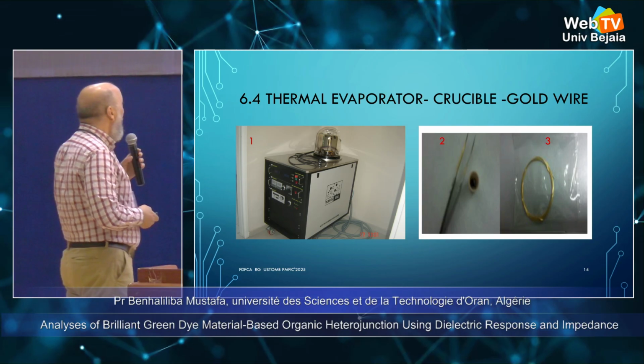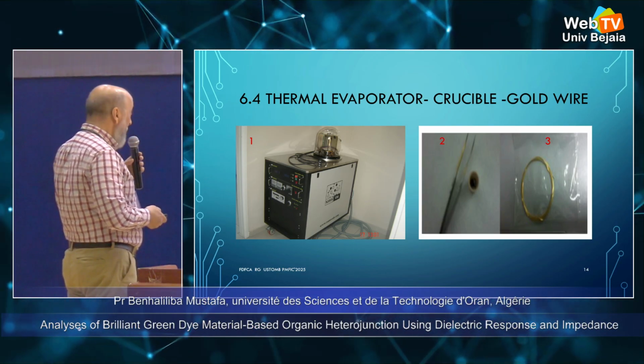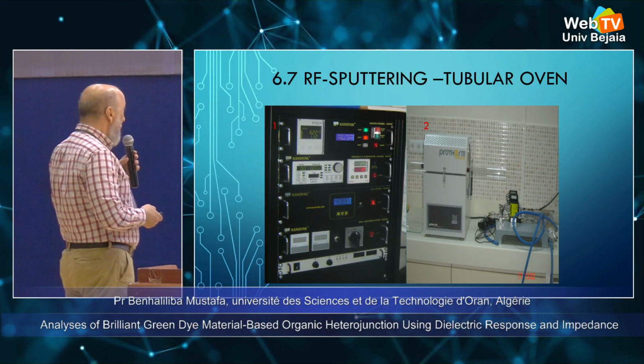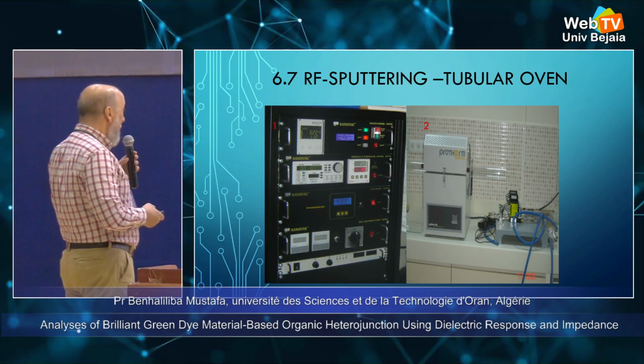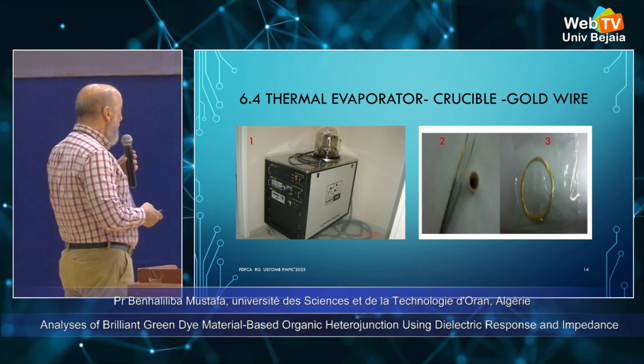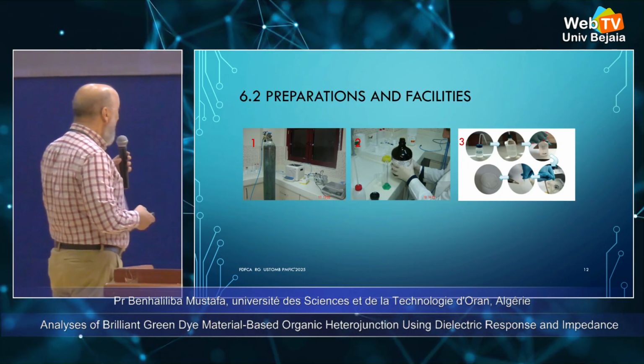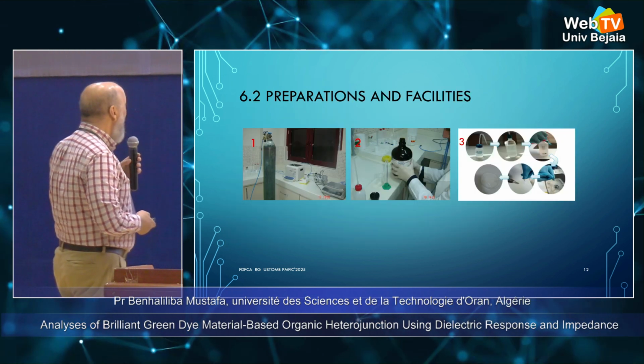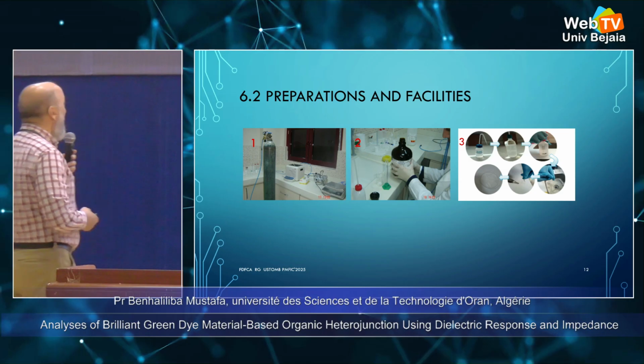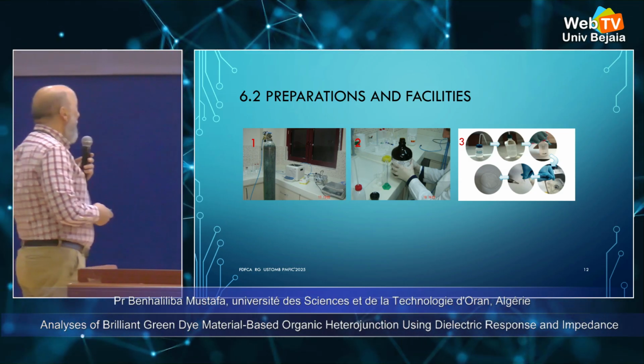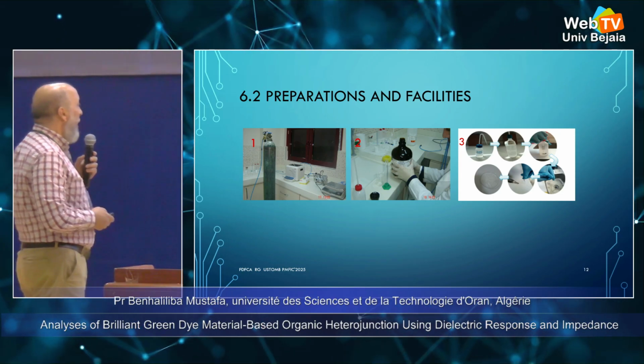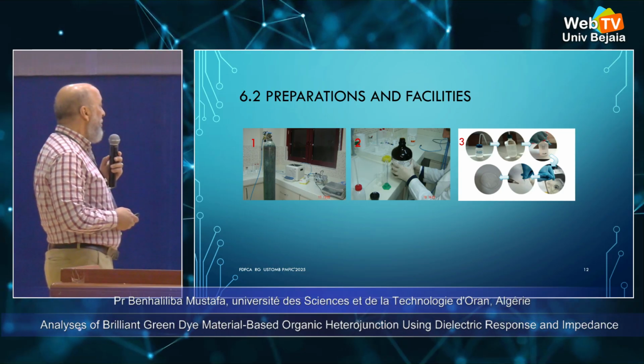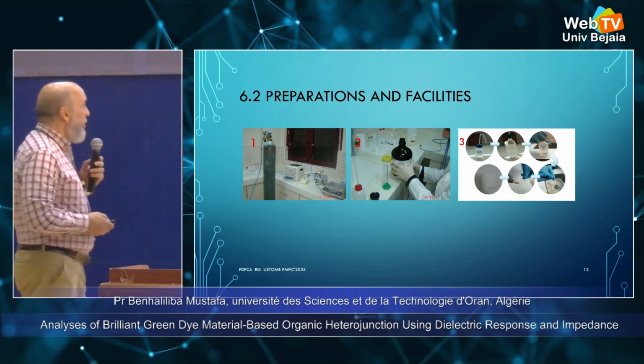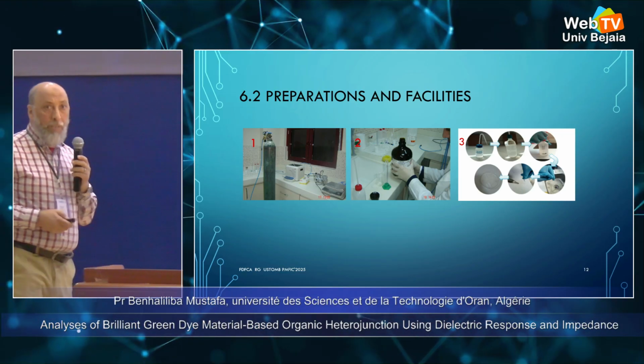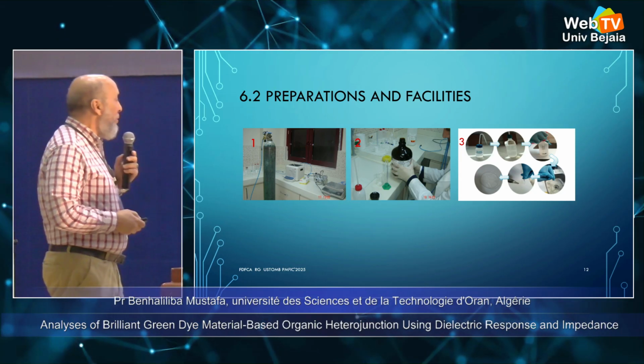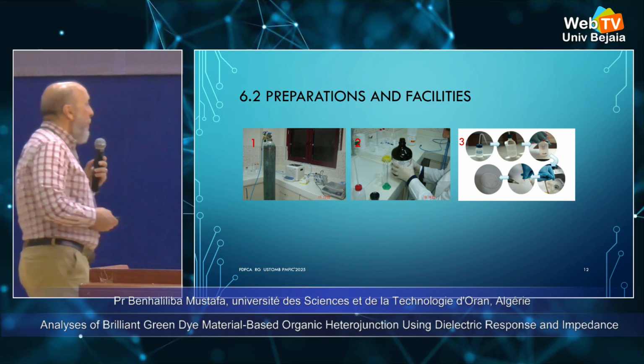Preparation. Here we display the different steps of preparation. In figure one, we have the spin coater, and in two, the preparation of the solution. In three, we have different steps of cleaning the substrate by deionized water, by acetone, and then we dry it with nitrogen.